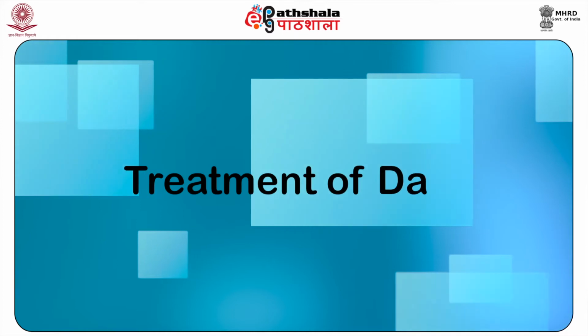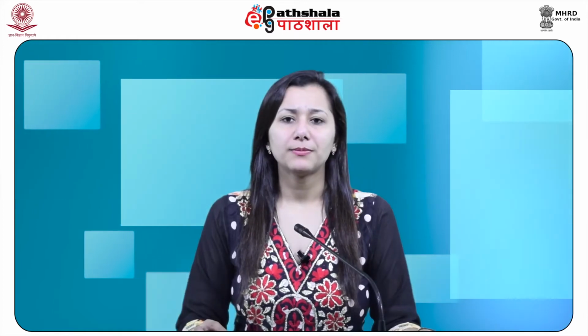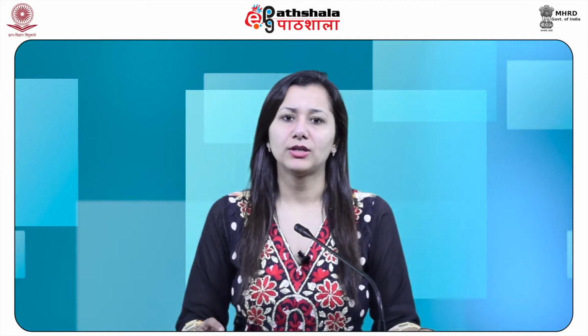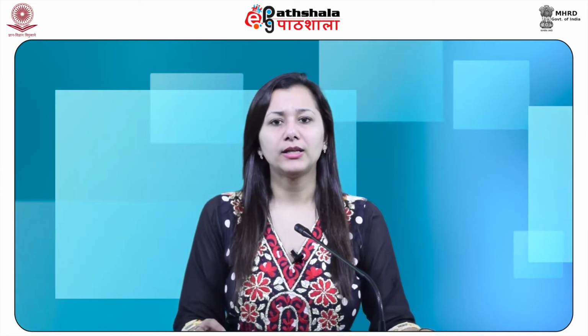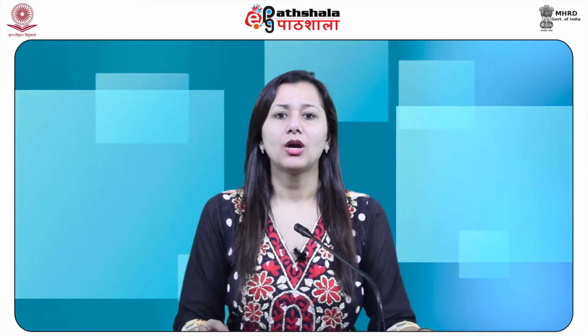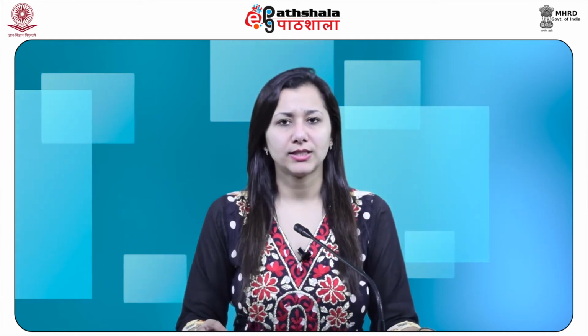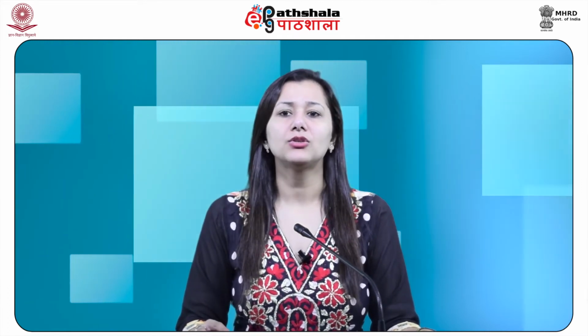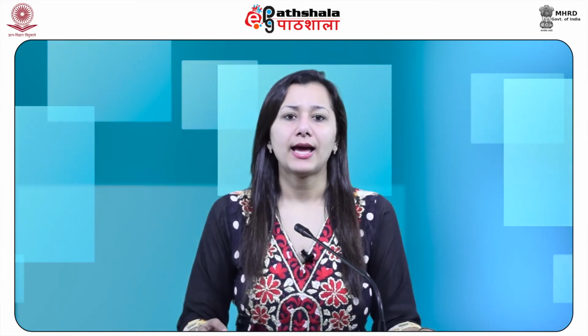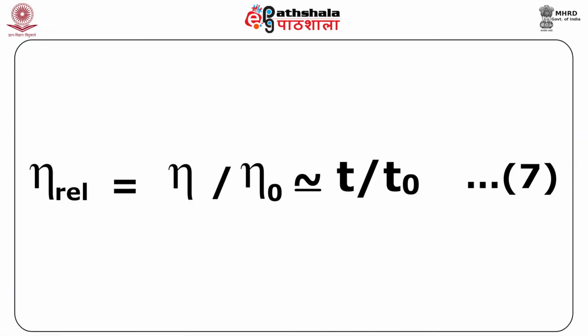Now we shall have a look at the treatment of data. Of the various methods used for determination of molar masses of macromolecules, the viscosity method introduced by Staudinger is the most frequently used method in research. Accurate measurement of absolute viscosity is difficult, therefore it is convenient to measure the relative viscosity. Hence, relative viscosity is defined as eta relative equals eta by eta naught, which is approximately equal to t by t naught, as shown in equation 7, where eta and eta naught are respectively the viscosity of the solution and the viscosity of the solvent.